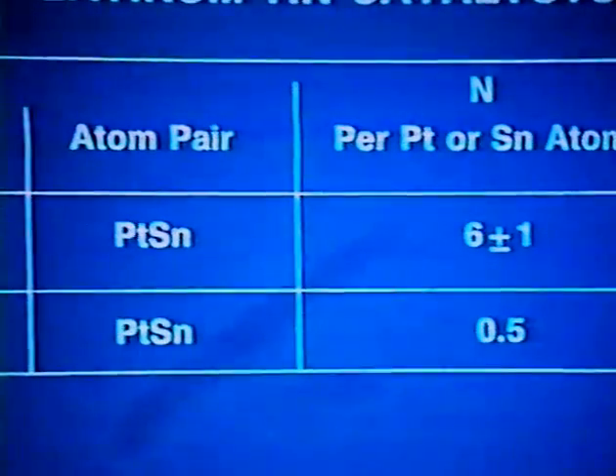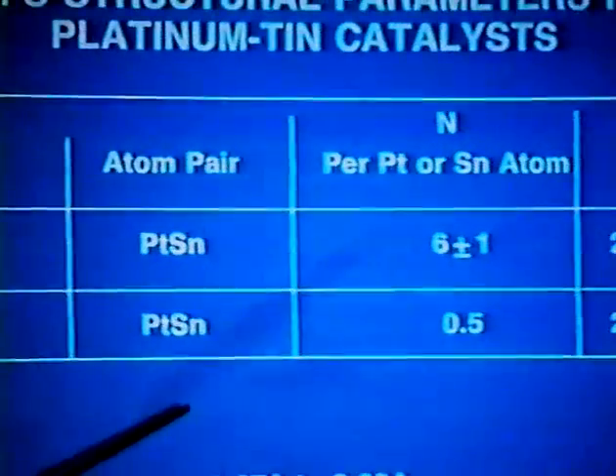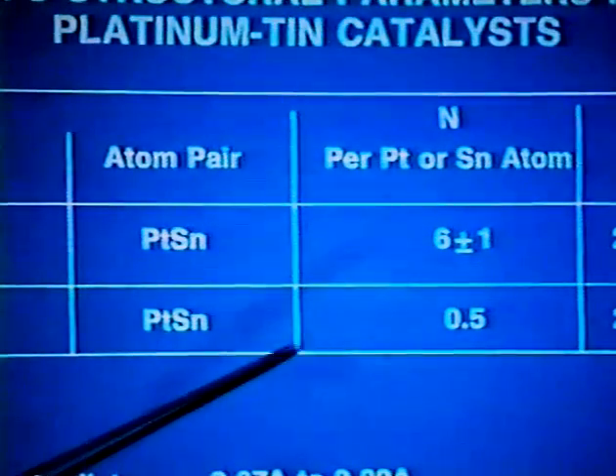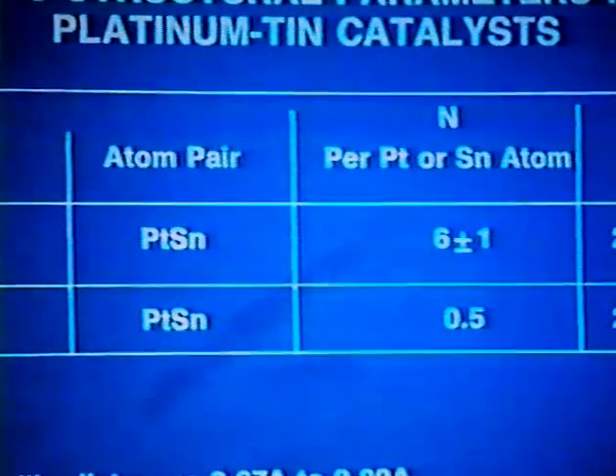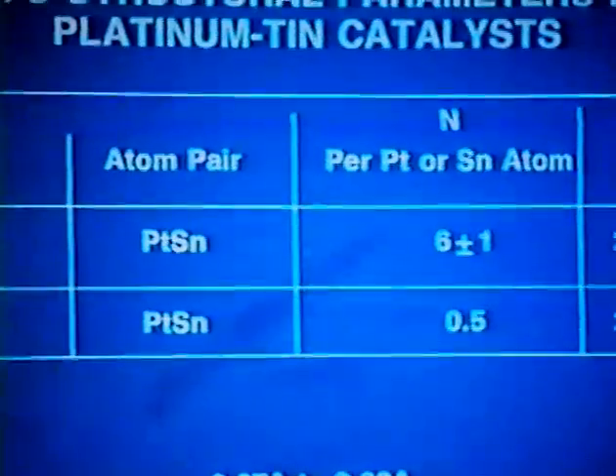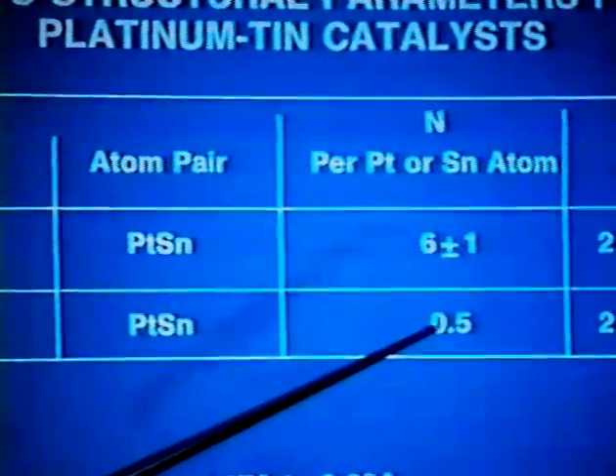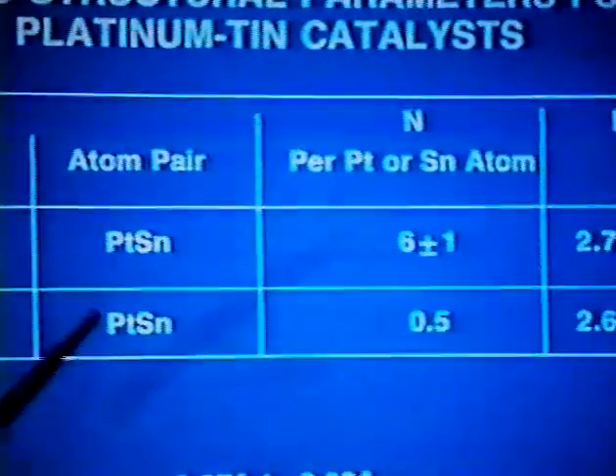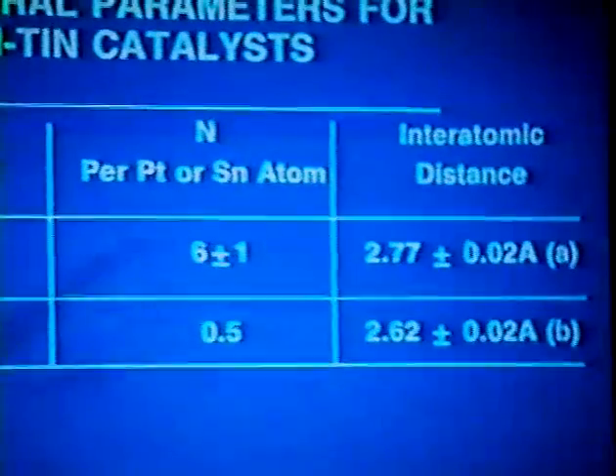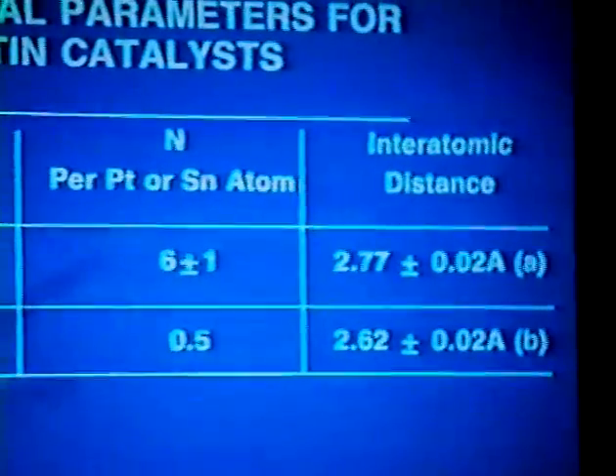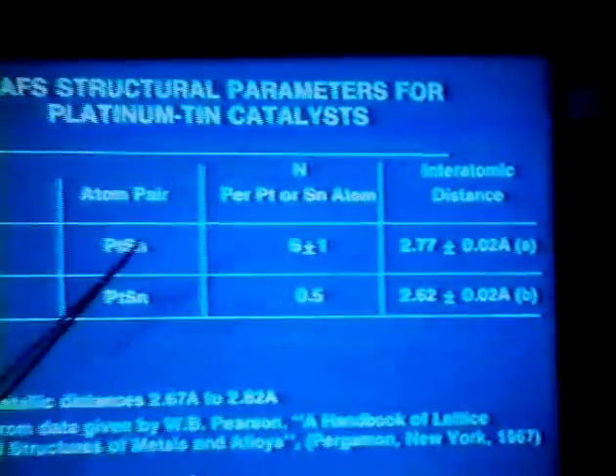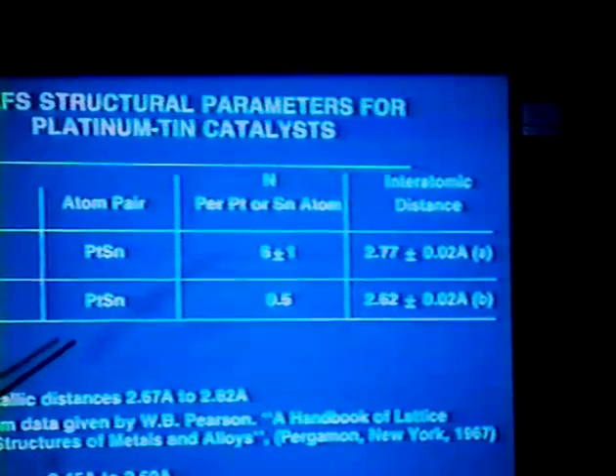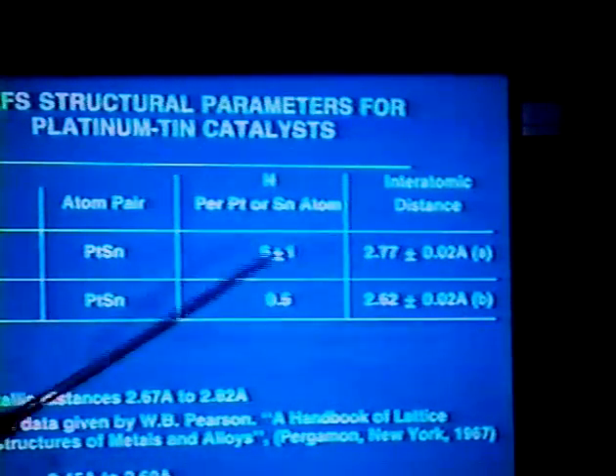We're looking at the platinum tin atom pairs in both cases. The number of tin neighbors of a platinum or a tin atom is about 6 in the platinum tin on silica system, and is about 1/2 in the platinum tin alumina system. That is to say, platinum has a fairly tin-rich environment. Tin has a fairly platinum-rich environment. Both of these have metallic environments. In the case of the alumina-supported system, they're not seeing very much of each other.